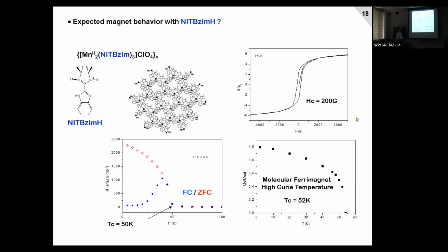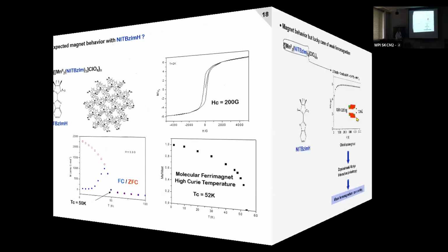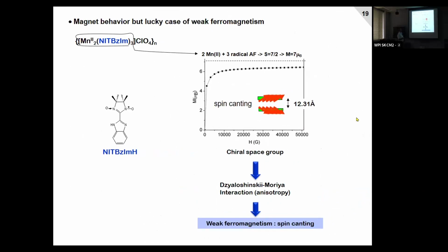So it is what we call weak ferromagnetism. And this weak ferromagnetism is certainly due to canting between the spins of the layer. So the spins of the layer are not completely orthogonal to the layer, but they are canted. And because they are canted, you have a resulting magnetization, but a small magnetization, which is why we have a small hysteresis.